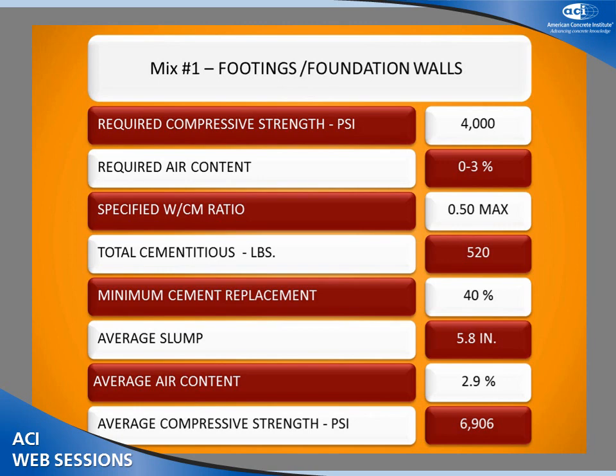On all of these mixes on the rec center, we had 30% fly ash replacement and 10% slag on each and every one of these that I'll show you here. Average slump with WRAs was at about 5.8. Normal air, this wasn't entrained, it was just entrapped. And you can see the compressive strengths were pretty impressive.